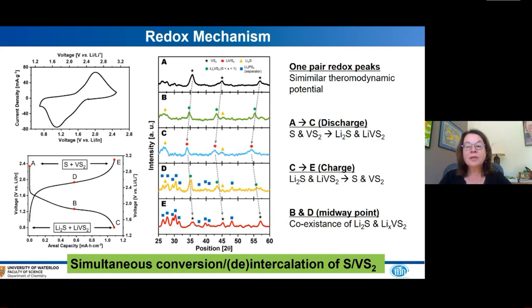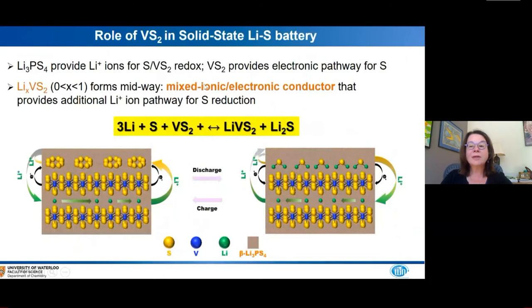The take-home message here is that we have simultaneous conversion and deintercalation of sulfur and VS2 in this system, shown schematically here. In summary, the Li3PS4 provides lithium ions for the redox reaction, the VS2 provides the electronic pathway, and the LixVS2 that forms midway is a mixed ionic electronic conductor. This is really well known for most of you in the audience, and this provides yet an additional ion pathway for sulfur reduction. So the overall reaction can be described as the following.